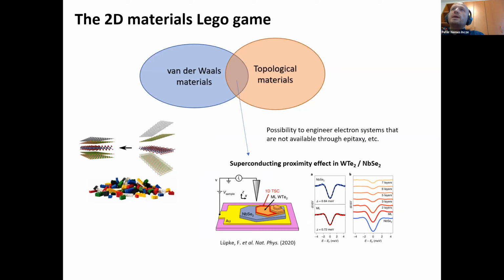And I've just picked out this one example to show you the power of this kind of stacking and this playing around with these materials, like with Lego blocks. And this is a very nice experiment from the group of Benjamin Hunt in the US, where they placed tungsten ditelluride on top of niobium selenide. And some of you may know that niobium selenide is a superconductor, and tungsten ditelluride is a 2D topological insulator. So what you can do is, through the proximity effect, you can induce superconductivity in the edge channels of this tungsten ditelluride. And it just takes one small leap of the imagination to go further with this kind of physics and this kind of building with Lego blocks.